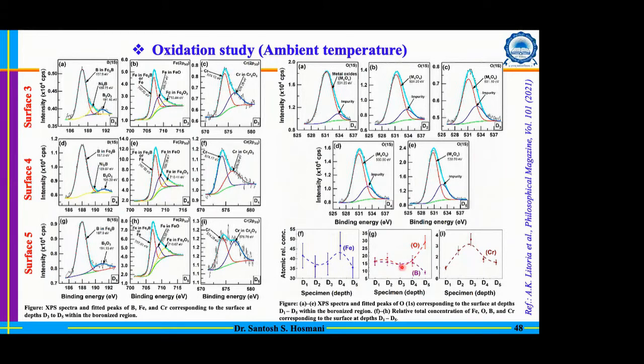That means your composition of the steel is also playing a role in governing the resistance to the ambient atmosphere. So the composition is very important, especially with respect to the migration behavior. That means you have migration behavior due to the accumulation into the matrix as well as into the boride phase. And in this case, the chromium presence in the boride is helping us to resist the oxidizing environment at ambient temperature.